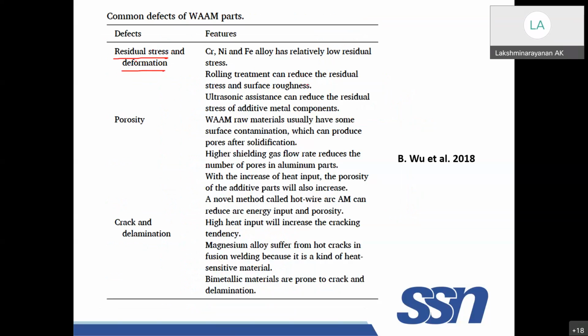That is because if you deposit a layer initially, and again I deposit another layer, some of the earlier layer will be melted again, and it will be at a particular temperature. It is not at room temperature now, because it is undergoing cooling. There will be an interpass temperature. Again another layer like that, and there will be accumulation of heat. So that sometimes causes the stresses built within this material to exceed the yield point of the material.